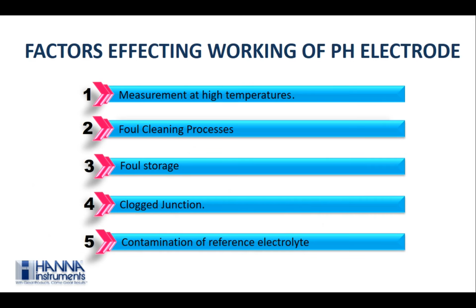The first factor that affects the working of a pH electrode can be high temperature. Continuous monitoring at high temperatures can reduce the life to almost one-fourth of the expected life compared to operation at ambient temperature. If you are continuously using an electrode at 80 or 90 degrees, you will be able to utilize the electrode for 1 month only. After 1 month, the electrode will start giving errors or erratic readings, and you cannot identify the exact reason.